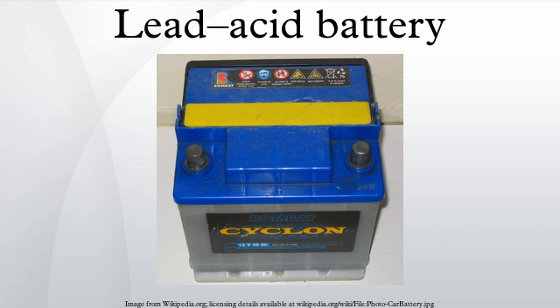soaked in electrolyte. There is only enough electrolyte in the mat to keep it wet, and if the battery is punctured the electrolyte will not flow out of the mats. Likewise, the mat greatly reduces evaporation, to the point that the batteries do not require periodic refilling of the water. This combination of features allows the battery to be completely sealed, which makes them useful in portable devices and similar roles. To address the formation of hydrogen gas during discharge, calcium is added to the plates to absorb the gas. This only works during slow discharges, and gas buildup remains a problem when the battery is deeply or rapidly discharged.